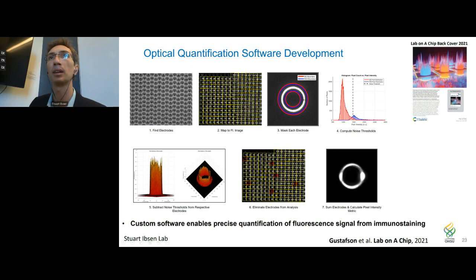And then we look at the fluorescence inside of this designated area that covers the ring around the electrode edge and compare it to the fluorescence in the background area outside of this region. And that allows us to create a histogram of the fluorescence intensities around the electrode edge where we expect sample to be located, and then subtract that from any background signal that might be present, allowing us to define the background level here shown by this black plane that gives us true signal that allows us to make really fine and very precise measurements of the fluorescence intensity, which corresponds to how much expression there is of that particular biomarker.